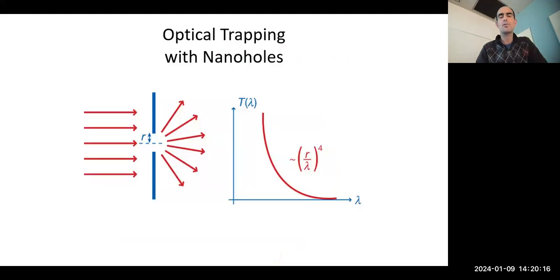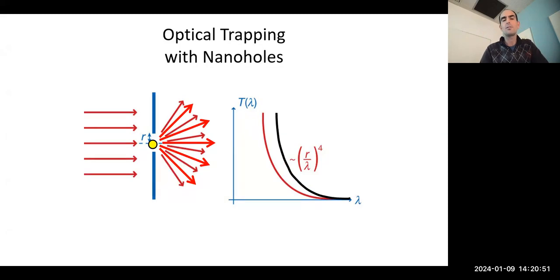So what do we do? We use apertures in metal films. The reason is that there you can isolate just a single particle inside the aperture, which has a smaller size because the aperture itself is nanoscale. The apertures don't allow much light to transmit, so when you put a particle inside them, they transmit more light because you're effectively making the aperture optically larger. This goes as the fourth power of the aperture size, from Bethe's aperture theory, giving a very strong scaling in the amount of light transmitted — even stronger than the third-power polarizability scaling I showed before.